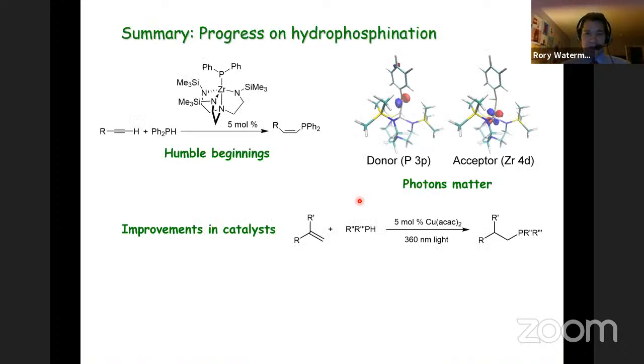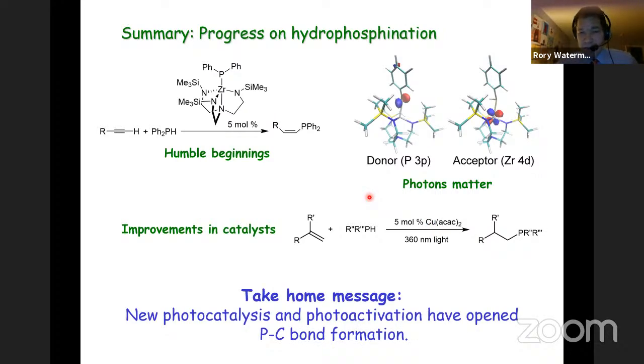And with that, I just want to summarize. So as I mentioned earlier, we weren't really good at this reaction, and we let it go for a little while, which I think was probably the best thing as opposed to hammering at it arbitrarily. And from there, what we really discovered, and that was the most critical part, was that photolysis was essential, and understanding, in fact, that there was the ligand metal charge transfer that drives the reaction taught us a great deal about how to turn on this. And then armed with that, photons really can do something, we're able to discover inexpensive, simple, available catalysts for this transformation. And overall, I think that supports this idea that photocatalysis and photoactivation are going to be very important for P-C bond formation in the future.